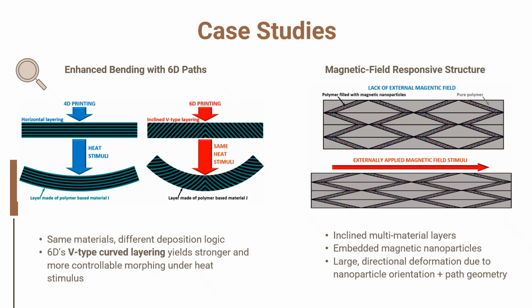On the right, we see a magnetic field responsive structure. Here, inclined multi-material layers contain magnetic nanoparticles embedded within a polymer matrix. Without a magnetic field, the structure remains static, but when a field is applied, the nanoparticles align and interact with the curved layer geometry, producing large directional deformation. Again, the key is the synergy between the smart materials and toolpath orientation. These two examples show that 6D printing does not rely on exotic materials alone. The intelligence emerges from the combination of smart materials and multi-axis deposition. The result is a highly tunable, functional, and adaptive structure that previous AM paradigms simply cannot produce.